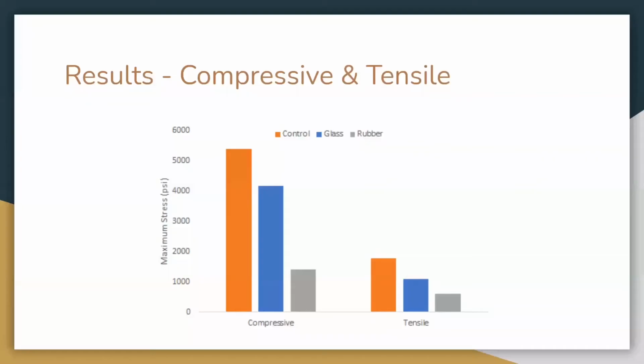Let's go. After compiling the data collected from the compressive and tensile tests, we calculated the maximum stress that each sample could withstand during both tests. Stress is a measurement of force per unit area, so samples of different size can be accurately compared. We can see that the glass sample's compressive strength was just a bit lower than the control, whereas the rubber sample was nearly a quarter of the control sample's compressive strength.